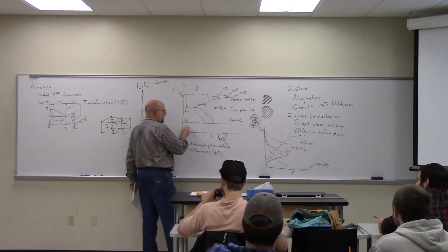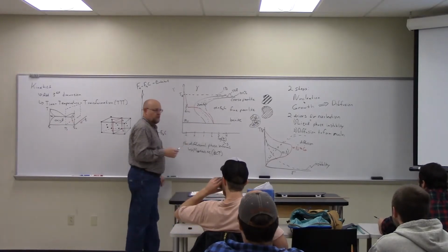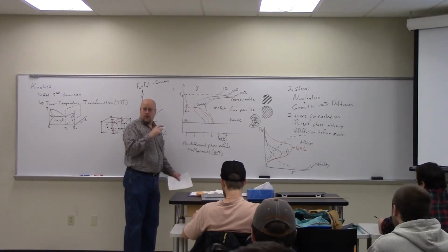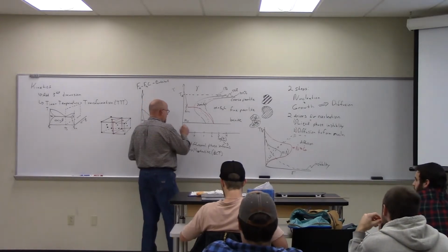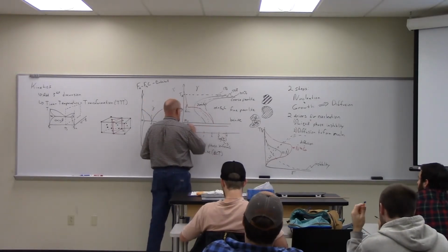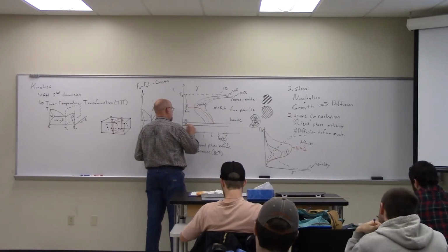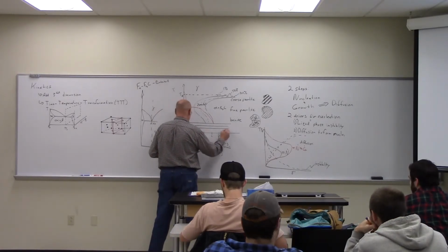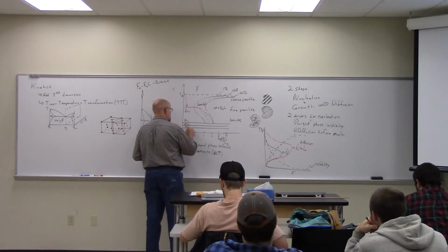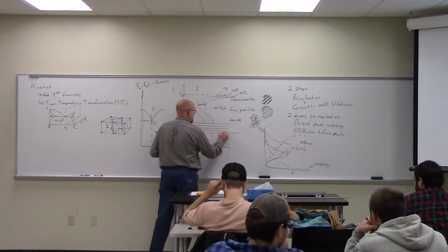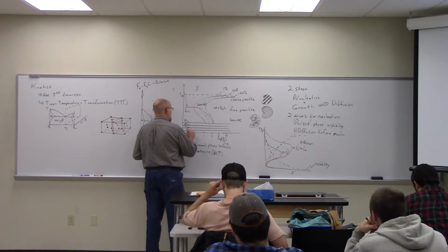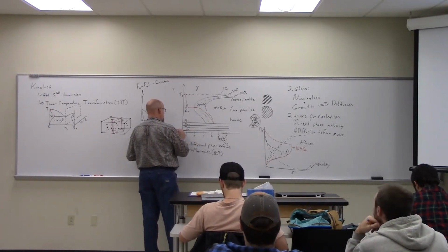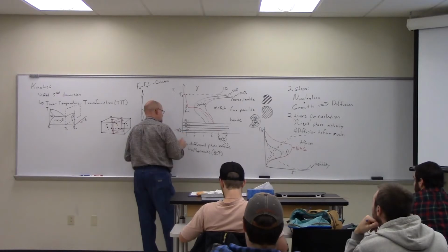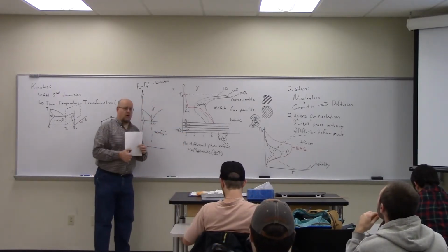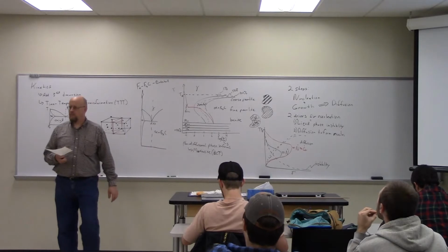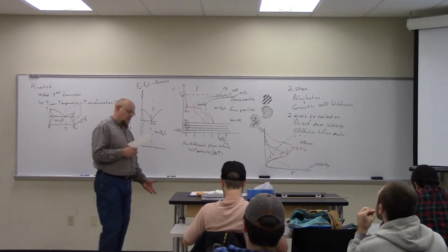All right, so we end up with this martensite region. Now, martensite also goes through a series of transformations, just like the pearlite formation. So you have an MS, an M50, which is 50% transformation, an M90, and then, if you go far enough, an M final. But this one is minus 46 degrees C. You go 46 below to get a completely transformed martensite. Okay, so it's not likely to happen.